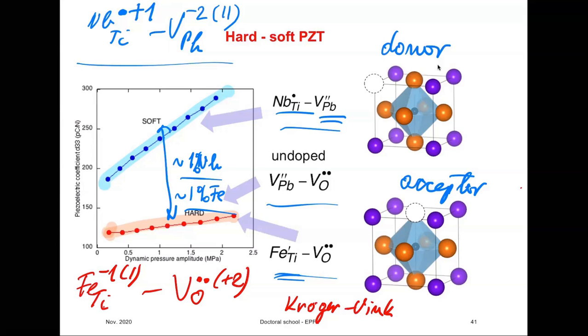So we believe that we know what the defect chemistry is in these materials, and this has been verified by electron paramagnetic resonance, by conductivity measurements, by annealing, and so on. It's pretty much clear that this is what's happening. But why does it lead to such a dramatic difference in the properties if it is enough to put just 1% of dopants, or even 0.1%? And why does pure material behave as a hard material?